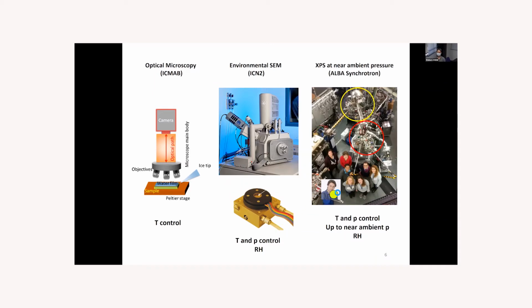And finally, we use the XPS at near ambient pressure at the ALBA synchrotron to study the water interaction with the surfaces in the ambient condition, because we have a control of temperature and pressure up to near ambient pressure.